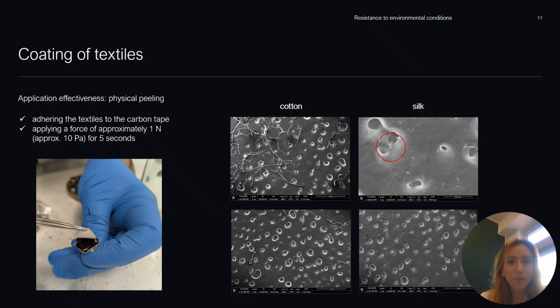And to answer the question whether the nanocomposite could detach from the textile structure, we performed a peel adhesion test. In this experiment, the functionalized textile sample was pressed against the carbon tape, as we can see here in this picture. The force used was around 1 Newton, and subsequently the sample was peeled away. This procedure was designed to simulate mechanical stress and evaluate stability of the nanocomposite coating on the textile fibers.